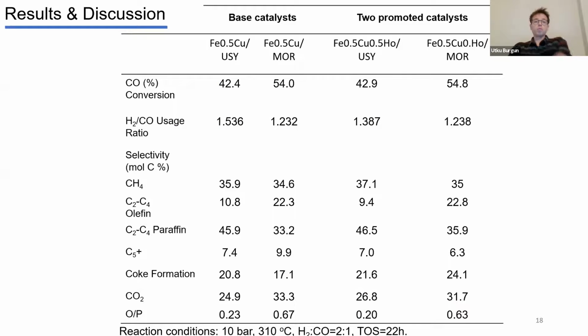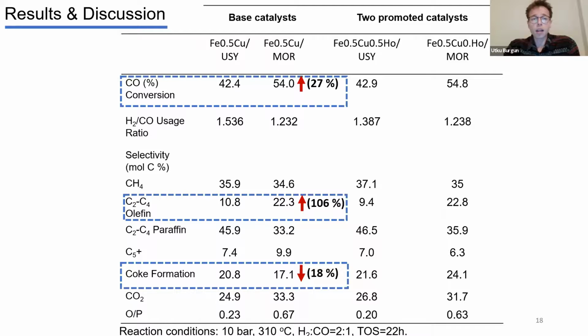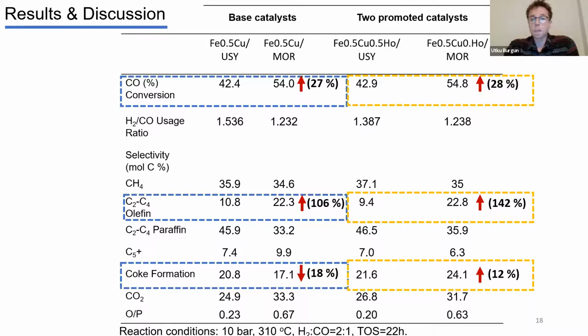So when we look at the overall results of the pressurized test system, on the left side, I mean the base catalyst, using the mordenite support increased the carbon monoxide conversion by 27%, and C2-C4 olefin selectivity by 106%. But here, using the mordenite support decreased the coke formation by 18%. And looking at the holmium promoted catalyst on mordenite support, it can be seen that the CO conversion increased by 28%, and C2-C4 olefin selectivity by 142%.